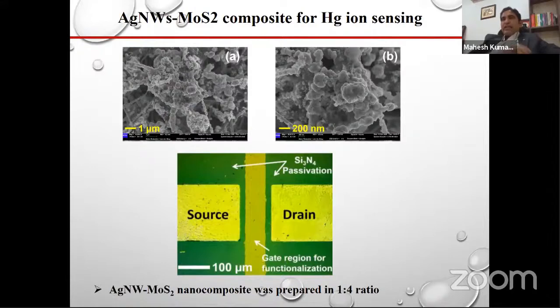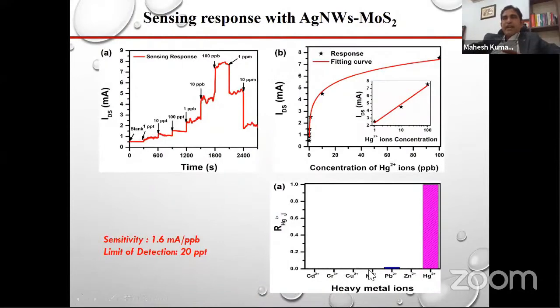Again, to improve this sensitivity further, because of how to transfer the charge from MoS2 to the electrode, we have used silver nanowires. We functionalized with the composition, and the optimized ratio we have taken is 1:4. Then we again did the measurement, and we found the sensitivity improved from microamperes to milliamperes just by using this nanocomposite.